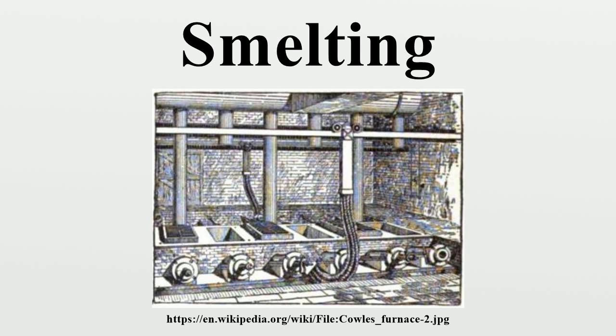While reverberatory furnaces were very good at producing slags containing very little copper, they were relatively energy inefficient and produced a low concentration of sulfur dioxide in their off-gases that made it difficult to capture, and consequently, they have been supplanted by a new generation of copper smelting technologies. More recent furnaces have been designed based upon bath smelting, top jetting, lance smelting, flash smelting and blast furnaces.